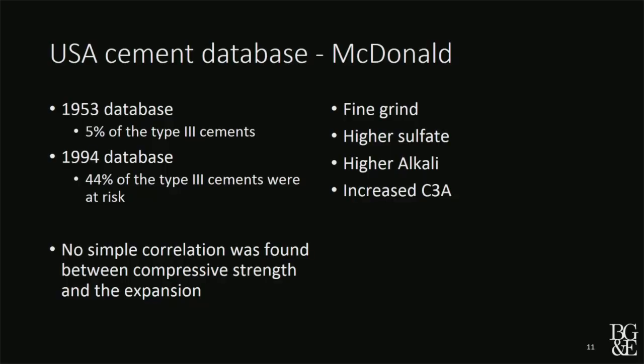So one of the things I did in the 90s was to take the equation that Kellam had developed and apply it to the cement databases. And in the United States, there were two cement databases that Portland Cement Association maintained. One was developed in 1953, and the other one was in 1994. And out of that research, I was able to show that there was an increase in the likelihood of delayed ettringite formation with the modern cements compared to the older cements. And this was attributed to the grinding, the higher sulfate, the higher alkali, and the increased C3A. Now, all of those four factors are great if you want strong concrete really fast.